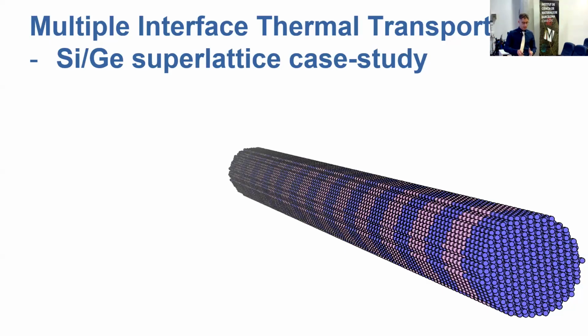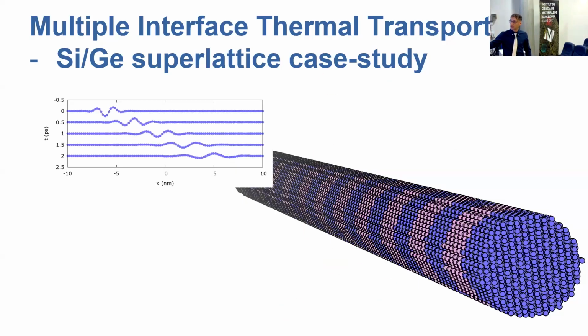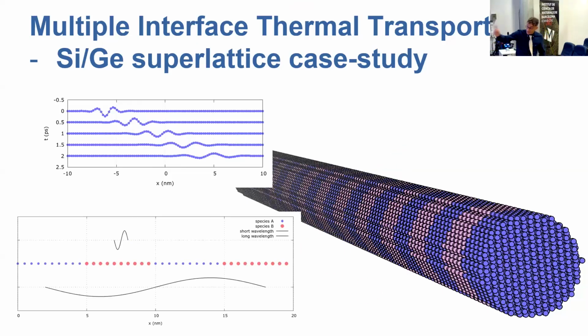A superlattice is basically a periodic arrangement of different materials at the nanoscale. Here I need to stress what a phonon is in this case. A phonon is a quasi-particle, meaning that it is an elementary excitation of the atomic lattice which possesses particle-like properties like a definite position, velocity, and extension. Now, in a simple lattice like this one, with only one atom kind, you don't have any length to compare with the phonon wavelength. But in a superlattice, the superlattice period introduces a scale. And this scale is exactly what allows us to talk about short and long wavelength phonons.